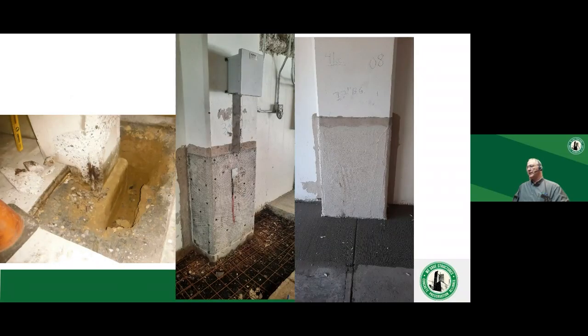Another area of concern is, like I was talking about, the columns. Here we had a problem where this is your footer, this is the joint. You had moisture and salt leaking down along the side, and it gets into that joint and starts corroding. If you notice, this is your dowel, and it's right at the edge. They bent it in, but it didn't protect it at the base. Right here at this joint, it started to corrode and it spalled the corner off. So now you've got corrosion activity right there, and corrosion activity on the other side.